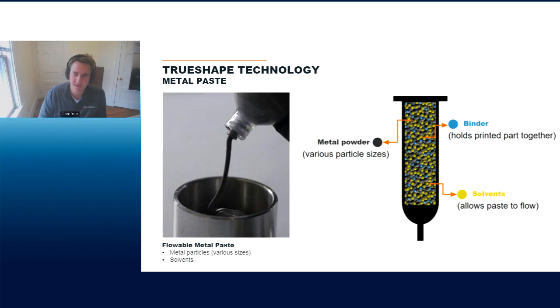Mantle is very unique in that a lot of metal 3D printers print powders, filaments, rods even. With Mantle's technology, we're printing a paste. You can see it on the left there. That paste is very similar to a toothpaste in terms of consistency. It's a viscous paste, and what this paste actually is, is a combination of metal powder mixed with solvent and binder. So we mix all of those ingredients together and it comes in a tube, and that's actually what we're printing in our process.